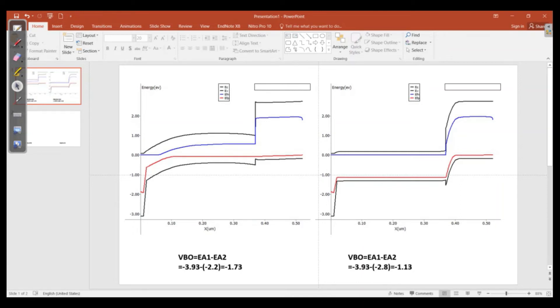This is one way to control the energy level of the material. It is important to keep a lower electron affinity value — at least 2.2 electron volts — for the Spiro layer in order to get higher efficiency in perovskite solar cells. This demonstrates the influence of electron affinity on device performance.